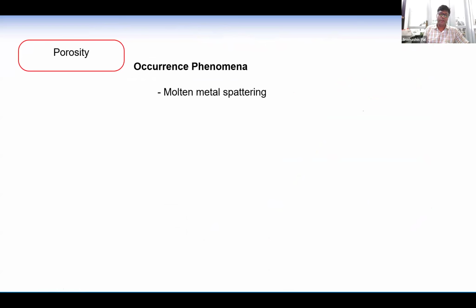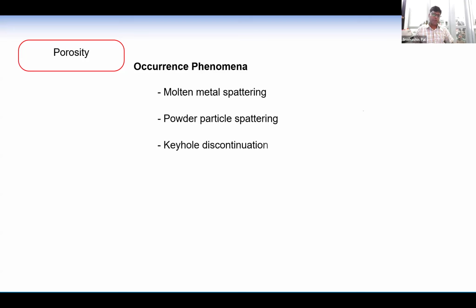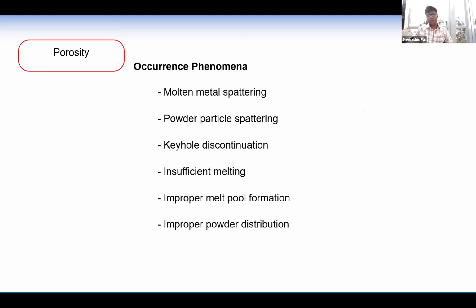So molten metal can sputter out from that place, and powder particles also can spread out, and some keyhole interruption can also occur there, and insufficient melting, or let's say improper melt pool formation, and maybe powder particles not distributed well by the recoater system, and gaseous bubbles can be interrupted, as it is known for the casting process, and also improper bonding between the layers, between the tracks, can also occur.